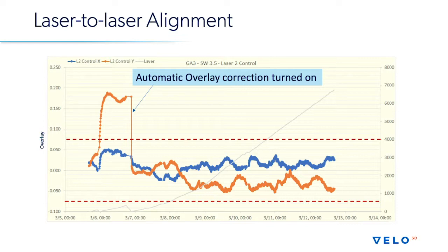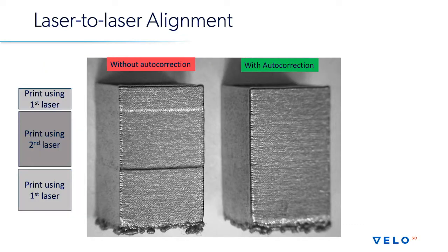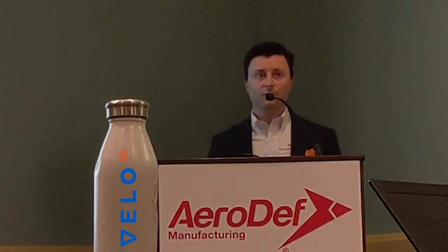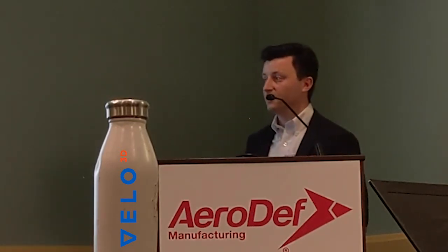What does that give you? It gives you a part with no discernible overlay. So you can actually build parts that look like they were printed with one laser. You're printing them with multiple lasers. And as long as you have this active control turned on, you more or less cannot see the overlay between the lasers. So it's a really effective tool, especially when you're building big parts.